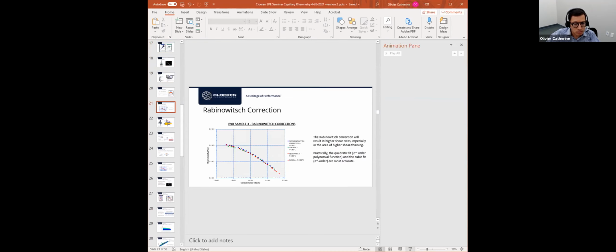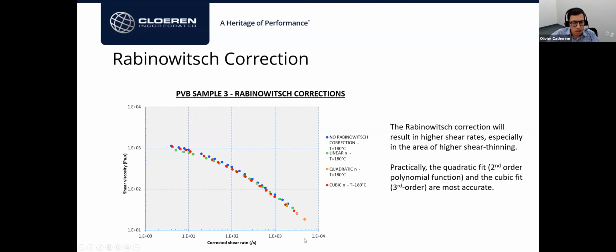Okay, so if you look at the uncorrected data and you look at the linear data, I did not like the linear data in this particular case. If you look at the data with the quadratic and the cubic, I think they are quite similar. Well, the quadratic seems to be stretched a little more. The shear rates are corrected more than the cubic in this case.